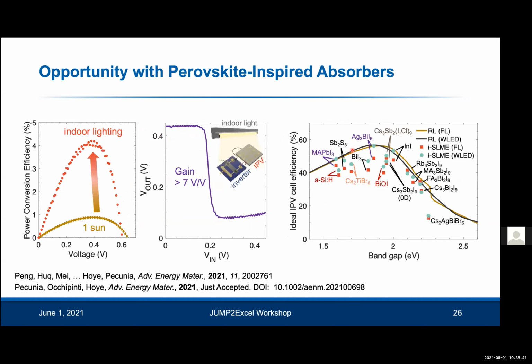And this area only recently emerged over the past few months, where I and colleagues looked at some emerging bismuth and antimony-based absorbers. And people have been looking at these materials as non-toxic alternatives to the perovskites for outdoor PV applications. And the efficiencies haven't been anywhere near as close as the perovskites, partly because these materials have wide band gaps, close to 1.9 eV. But that band gap actually is the optimum value for indoor light harvesting.